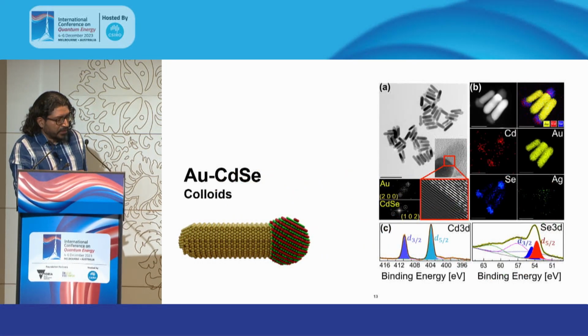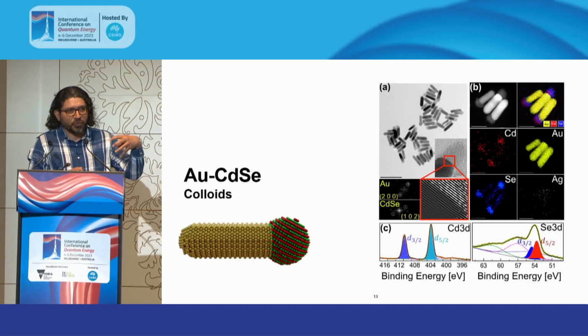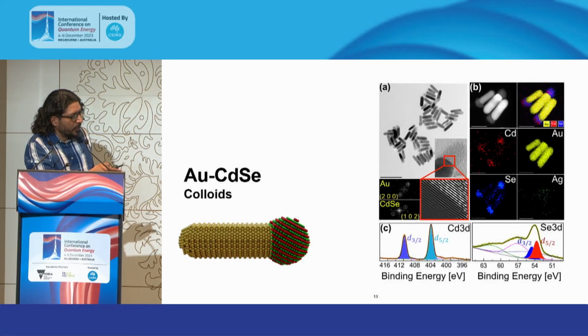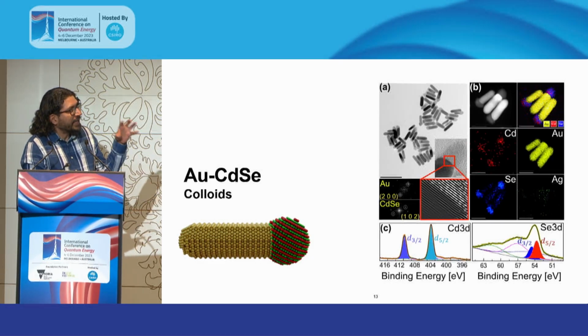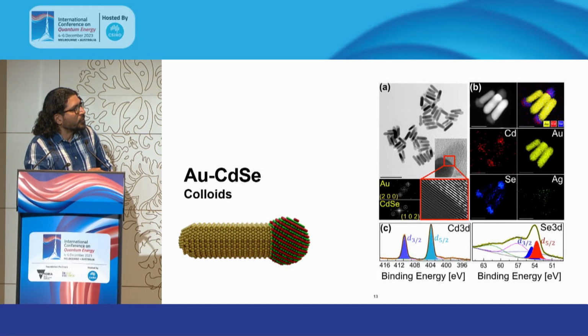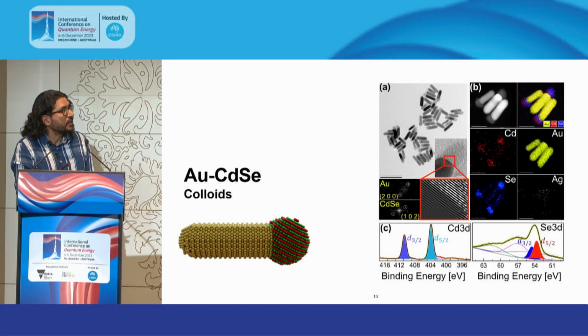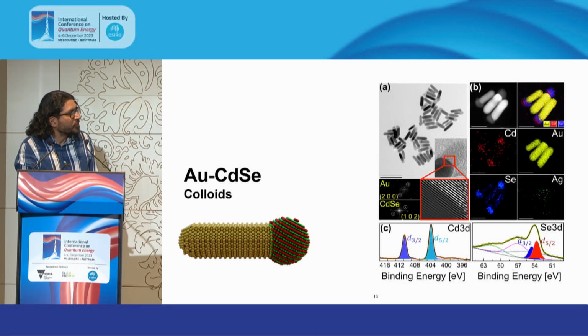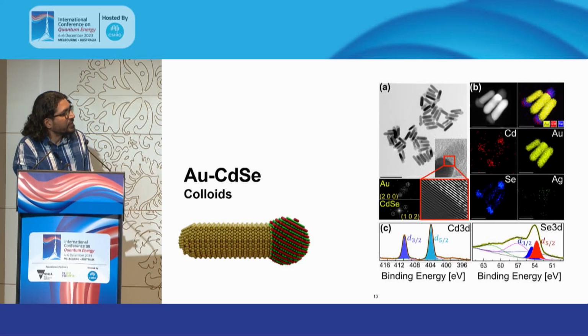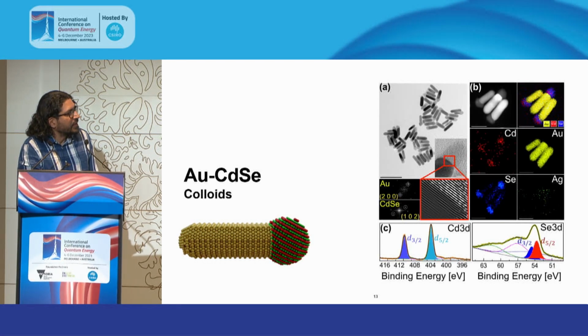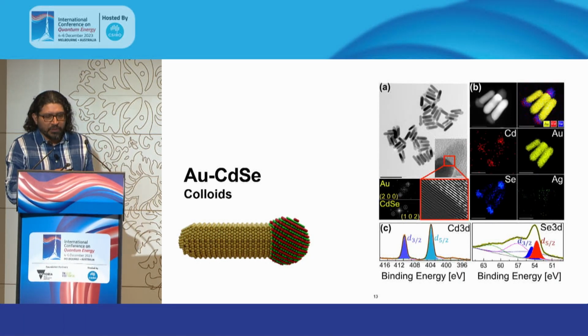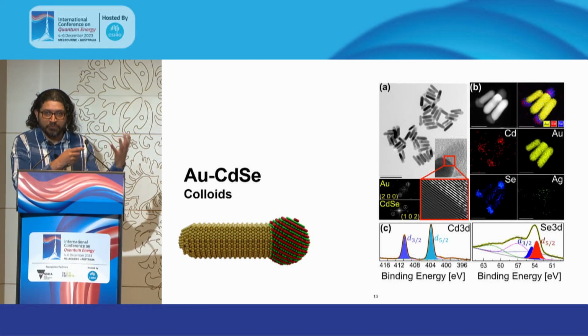Briefly, we grow these materials using colloidal chemistry. That is, we use solution-based approaches with water, metal salts, and precursors. We first grow the metal nanorods, and then by carefully tuning the chemical conditions, we grow the tips of the semiconductors on the one end of the rods with high fidelity. As in 90% of the product is the intended structure, and we have done a lot of characterization. There is heteroepitaxial growth. As you can see here, the crystallographic planes of everything seem to match very well. So these are actually nanocrystals, not just random particles.